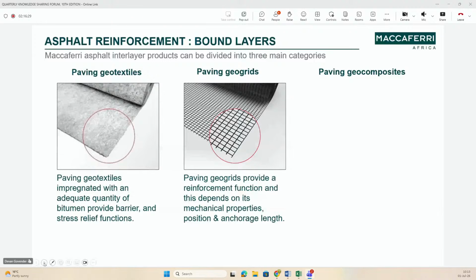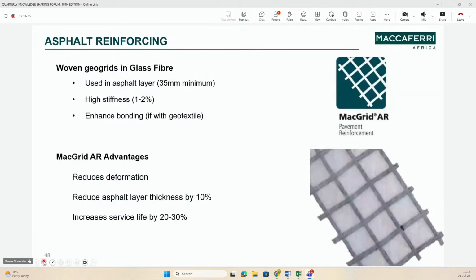Now, when we start looking at that material, we have woven geogrids. Importantly, we are talking about grids that are made from glass fibers, which can be used in asphalt layers that are about 35 millimeters. They have a very high stiffness. The characteristic of the material is that it's got to be stiff so that when you have deflection of that pavement, it reduces deflection. So it's still flexible, but it's reduced.